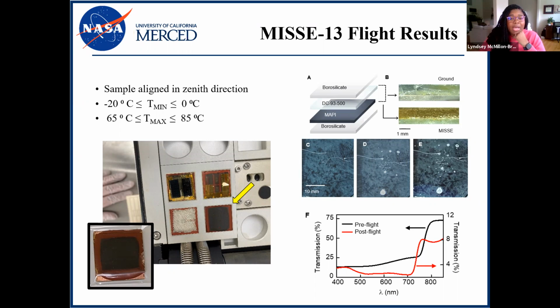C. So on panel B, I'm showing an edge-on photograph taken with a digital microscope. So the arrow on each image is aligned with where the encapsulant and the perovskite film are, and glass substrates are on either side. So the brown on the bottom image is actually a borosilicate substrate that darkened due to the UV exposure during the space flight. So images C, D, and E are photographs of the sample that were taken. The first one, image C, right after fabrication, so time is 0. D is 290 hours into the humidity experiment, and then figure E is post-flight.